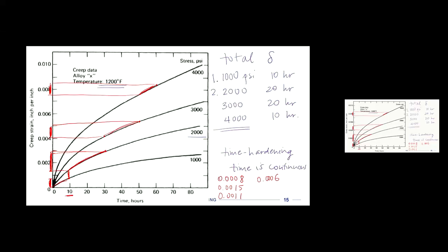Okay. So if we add all those up, we get 0.004. All right. And I realized I didn't get my 5-minute warning, so we are at the end of class time. I hear the zippers zipping. So we'll have to do the other two methods in the next class. But we'll end there for today. So you can see 0.4% creep, not too much. So that's a good value. And that is the time hardening method, time hardening rule.